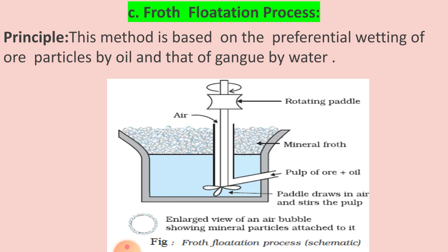So now the powder ore is added to the water containing pine oil, that is the frothing agent, and sodium ethyl xanthate, that is the collecting agent. Here cresol and anilines are also added, which stabilize the froth formed in this process. A vigorous stream of air is now passed through, which thoroughly agitates, that is mixes the mixture, and disperses the oil into colloidal sized particles. As a result of this, the sulfide particles of the ore stick to the oil droplets and rise to the surface in the form of froth supported by air bubbles.